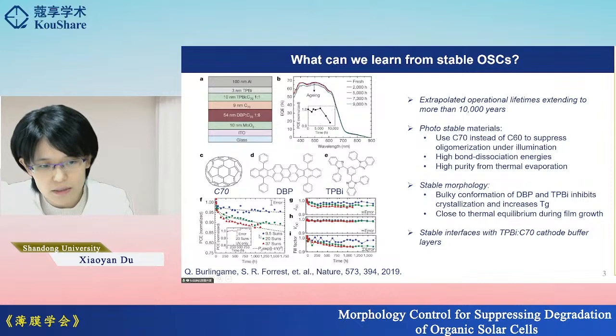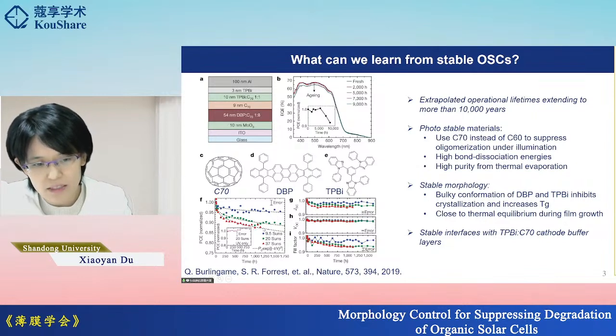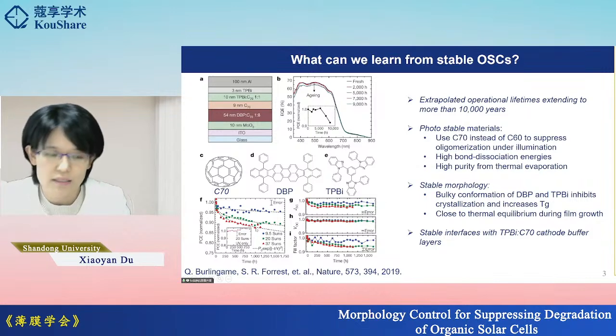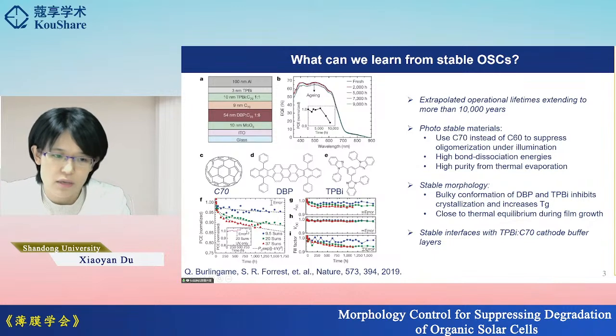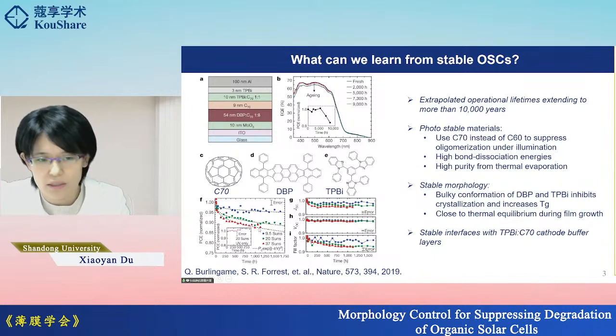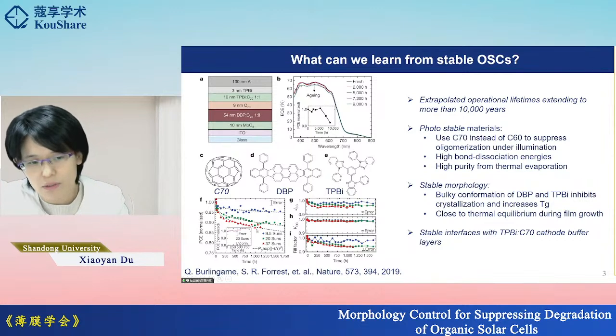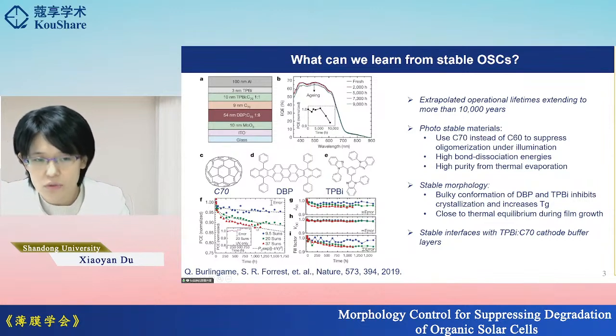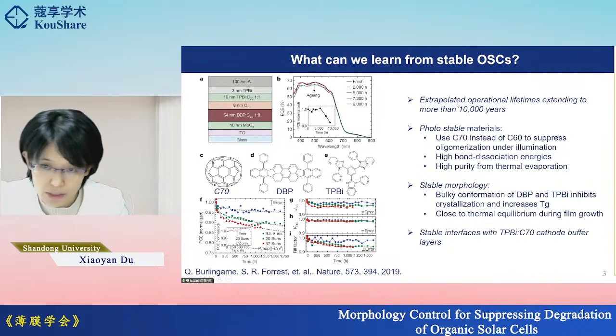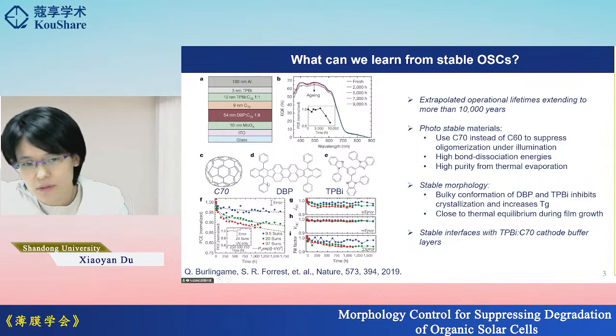This is the photoactive materials. And in this data, we see the photostability of the cells under different levels of concentrated light. And even under 37 times concentrated light, compared to the standard one sun intensity, this kind of solar cell still remains close to 90% efficiency after around 1,000 hours of illumination. And if we extrapolate the operational lifetime, it's extremely stable. So what makes the cells so stable?